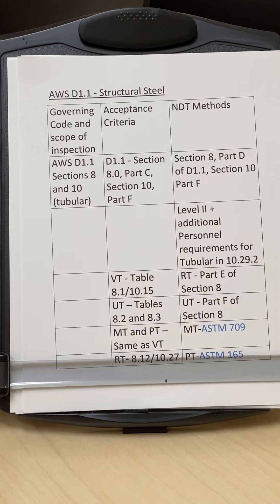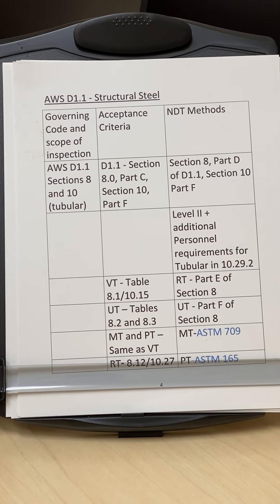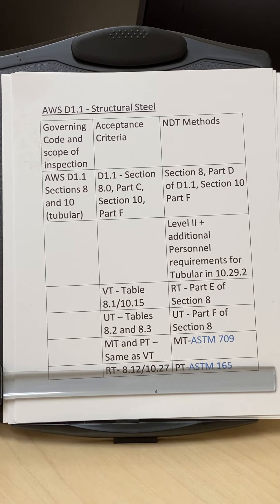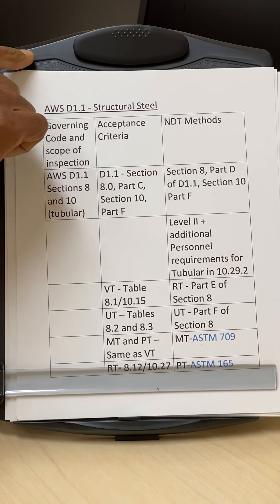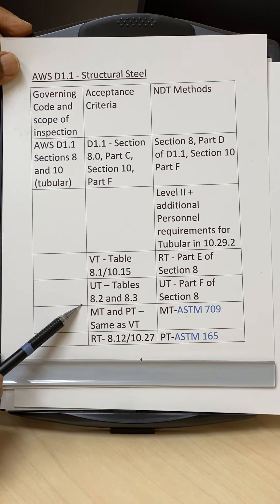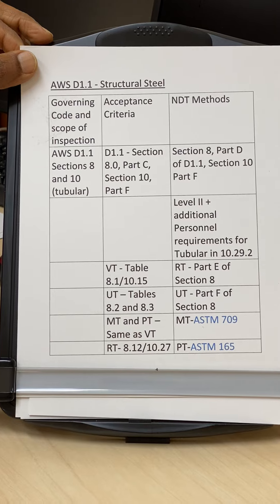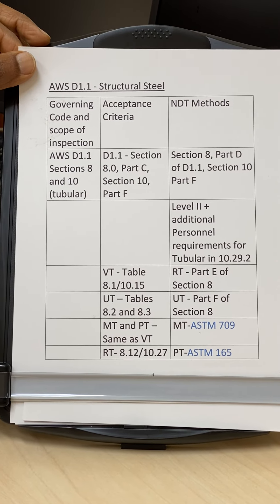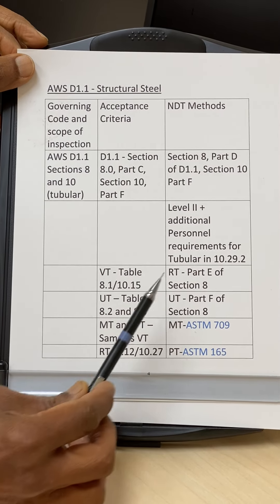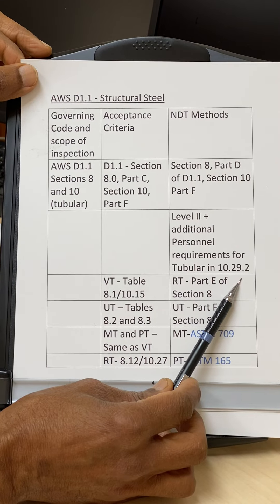At the end, the code provides the acceptance criteria. Once inspection is complete and a discontinuity is found, the code specifies the size so a decision can be made whether to accept or reject it. In D1.1, the two sections dealing with NDT inspection are Section 8 and Section 10. Section 10 pertains to tubular structures — TKY joints.